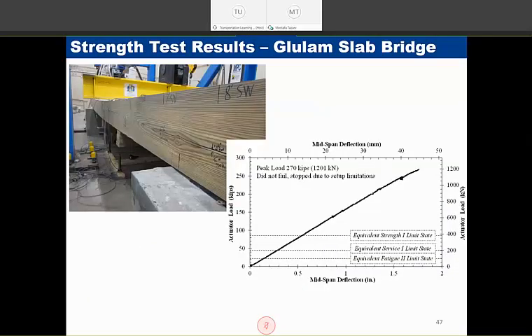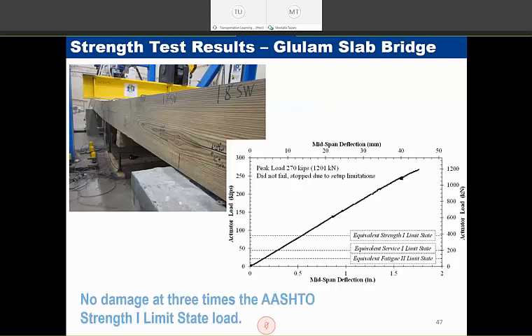We also strength tested the slab bridge. We went three times the actual strength limit state. The bridge did not fail. We stopped it. Here you can see the equivalent fatigue two limit state, equivalent service one limit state, and strength one limit state, all much lower than where we went. So the overall conclusion would be that this bridge has good capacity to take ultimate loads.